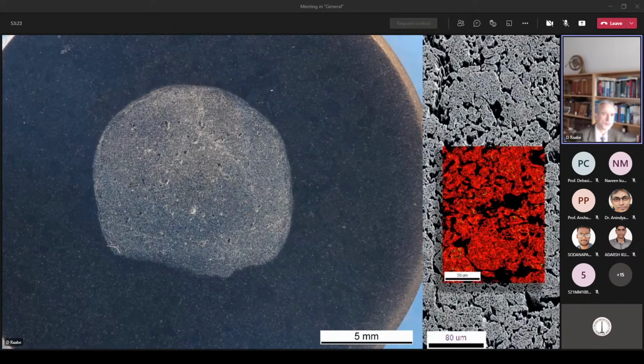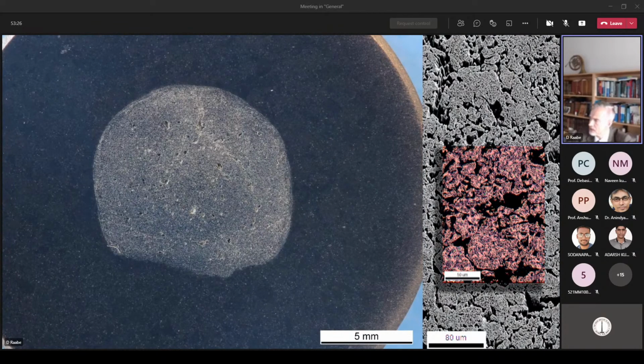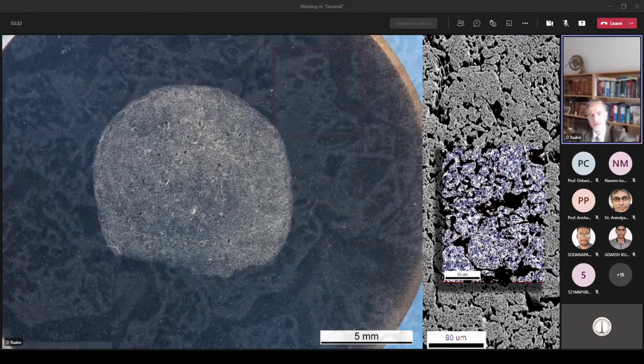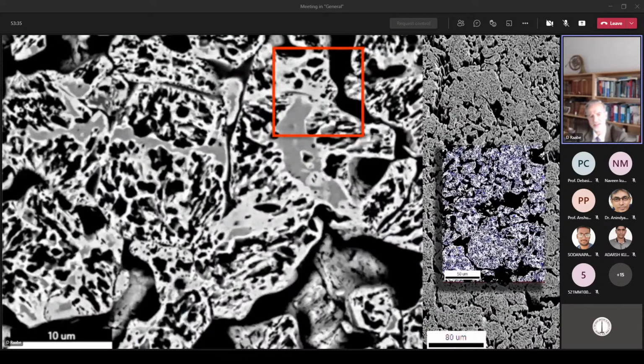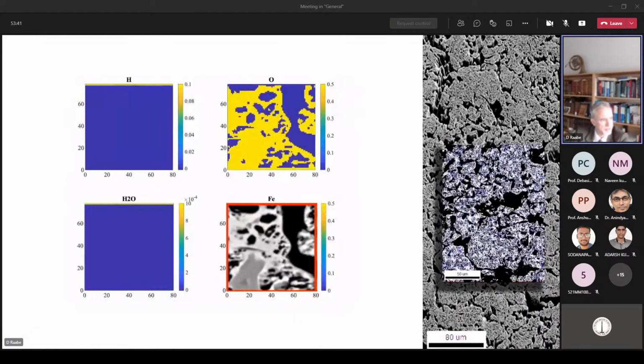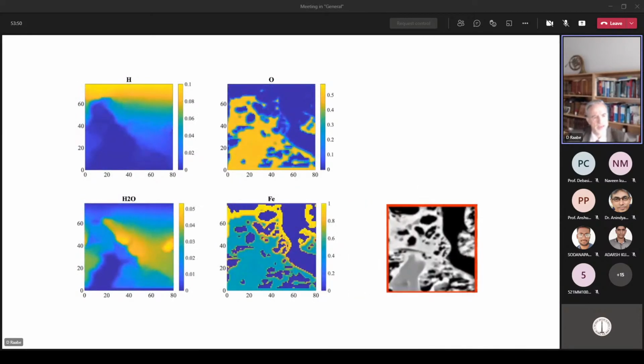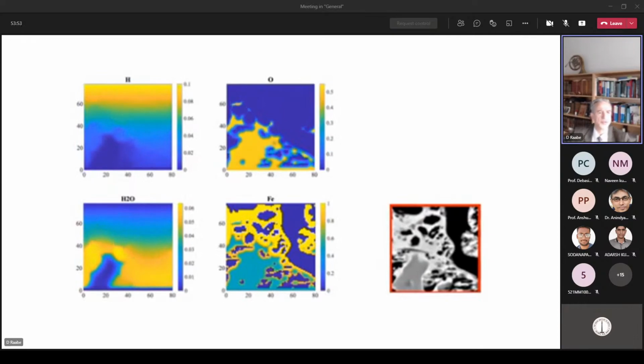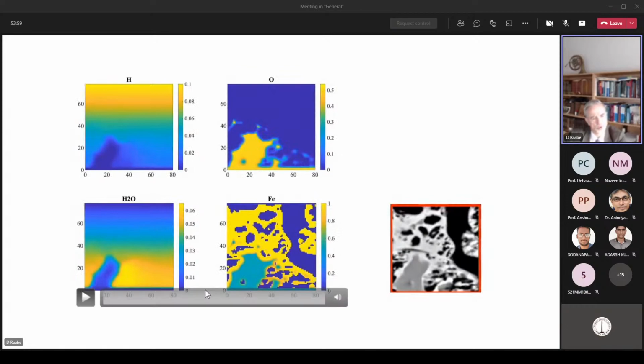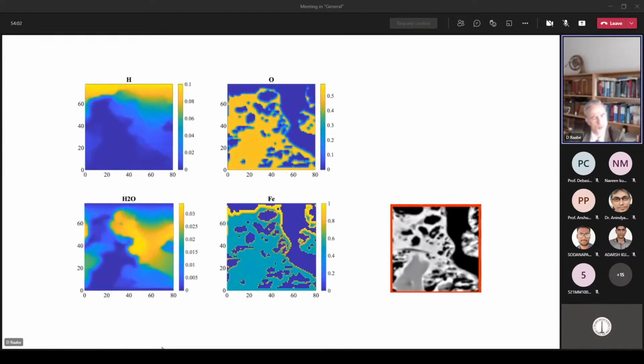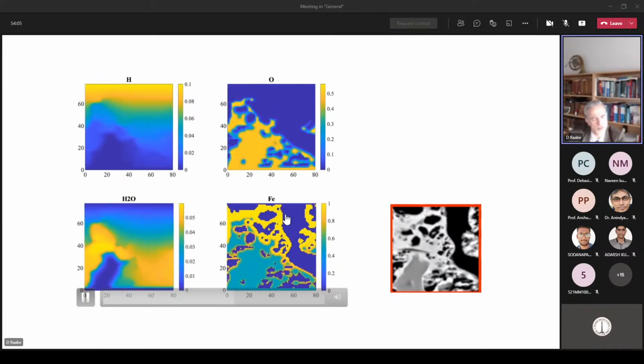Again, we do the same analysis. We map the microstructure, the phases, the grain boundary, and so on, as you see here in this slide sequence. And then we use this information as a starting point for a phase field calculation. So what we do here is a full field treatment where we use the phase transformation, of course, through the Allen-Cahn theory, which is a non-conserved structural phase field. And of course, the rest is the classical Cahn-Hilliard theory where you solve the diffusional problem. And with that, we try to simulate, as you see here, the progress in the growth of the iron when you expose that piece of wüstite material to hydrogen.